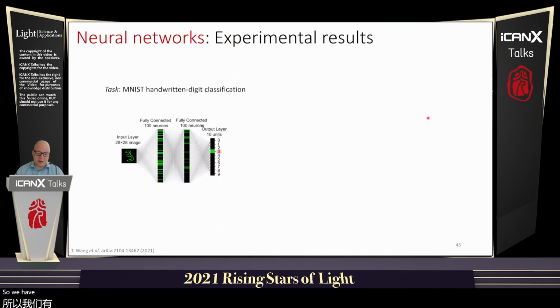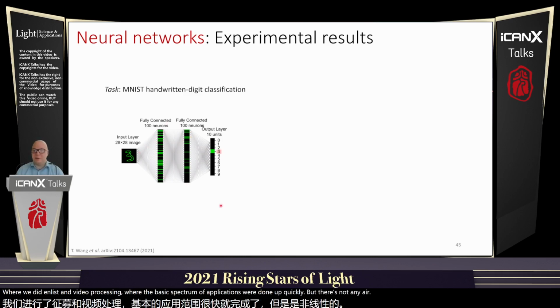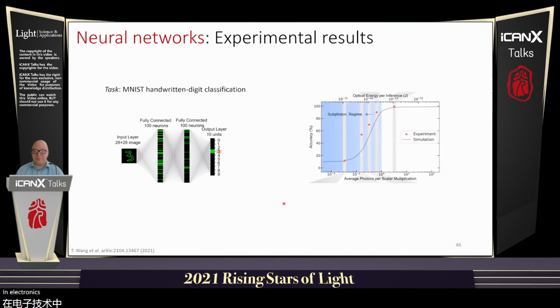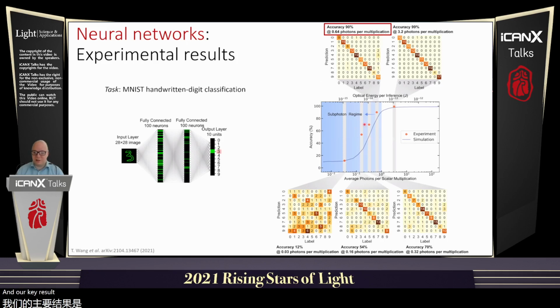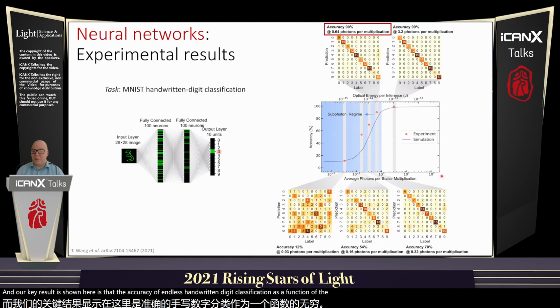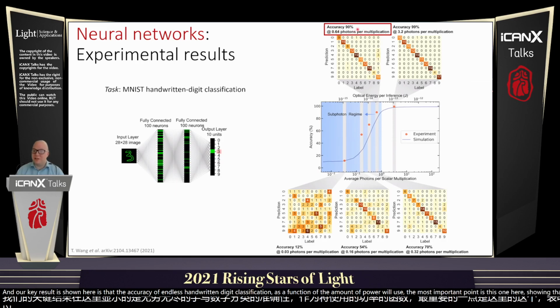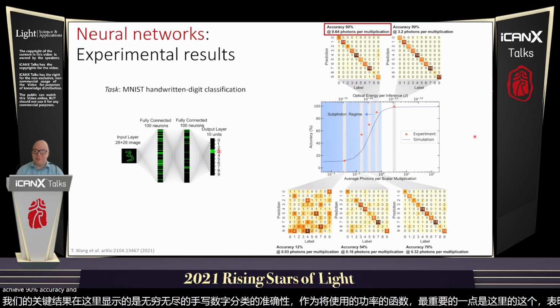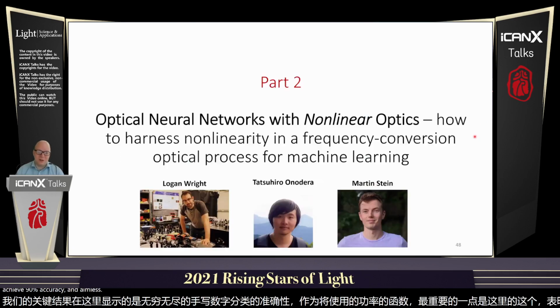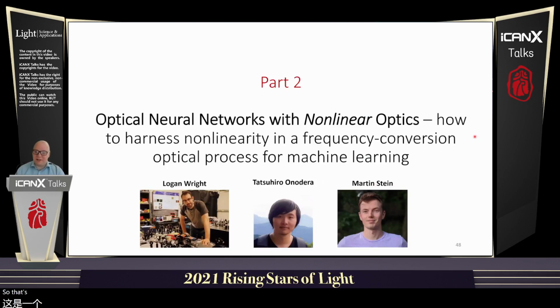So we've now done our own demonstration of this with our system, where we did MNIST handwritten digit processing, where the matrix vector multiplications were done optically, but the nonlinearity was applied in electronics. And our key result is shown here: the accuracy of MNIST handwritten digit classification as a function of the amount of power we use. The most important point is this one here, showing that with less than a photon per scalar multiplication, we can still achieve 90% accuracy in MNIST.